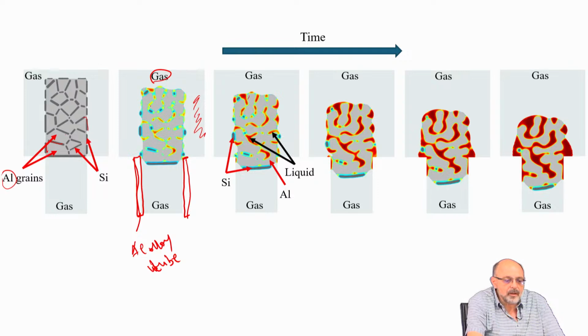So here's how the flow proceeds. Liquid is red. You see the melting around silicon, and it uses up that silicon fairly quickly, except this one at the bottom, right? So this was just a test run. We wanted to see how our flow and melting is working.